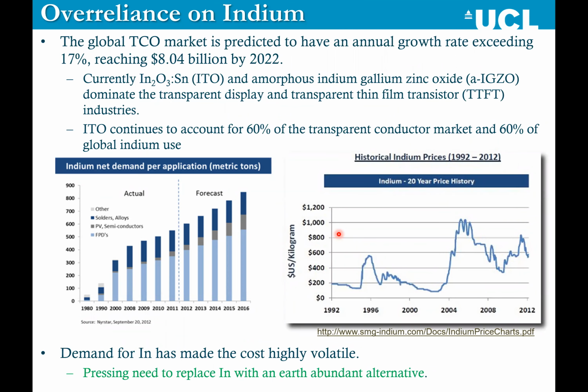So currently the field has a massive over-reliance on indium. The TCO market is growing hugely. It's a $1 billion industry, but currently it's dominated by tin-doped indium oxide, which we call ITO, and amorphous indium gallium zinc oxide. Any kind of thin film transistor display or transparent display normally is dominated by tin-doped indium oxide. And because of this, the net demand is increasing as people are buying more and more devices. I currently have 2 tablets and 3 laptops, so I'm adding to this problem myself.